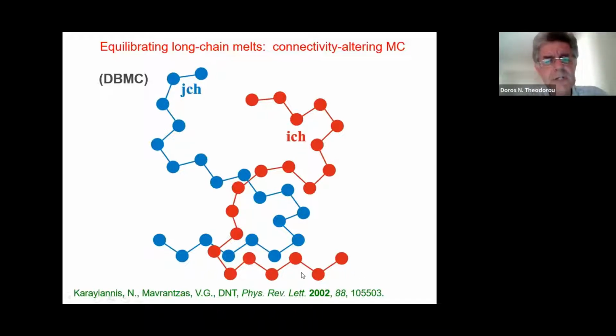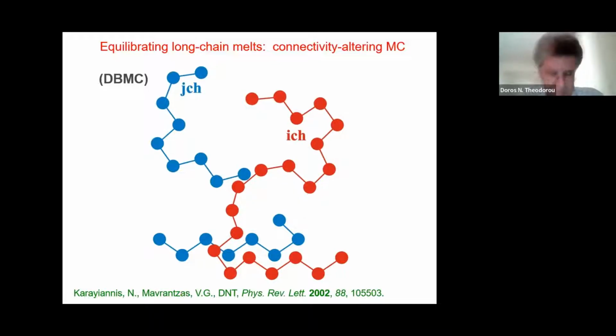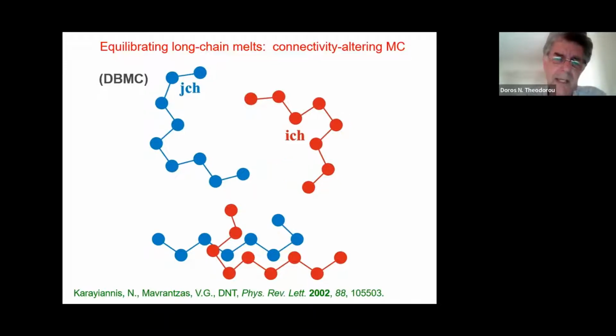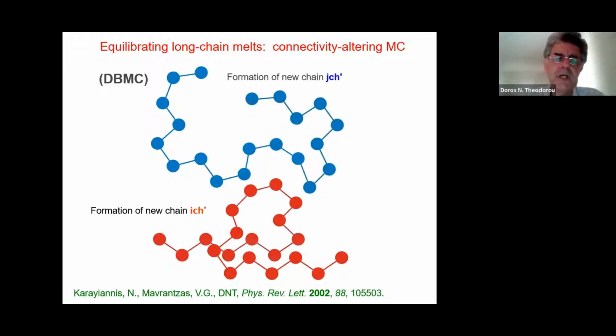Envision two chains near each other in the melt. We have a move which excises a trimer segment from the blue chain and a trimer segment from the red chain, and then builds two new trimer bridges to form two new chains, which have exactly the same length as the original ones, but very different conformation. So by using this kind of move, we are able to very boldly rearrange the long-range conformational properties of polymer melts. We are able to have very efficient sampling of these long-range conformational properties, and we can equilibrate a polymer melt orders of magnitude faster than molecular dynamics.